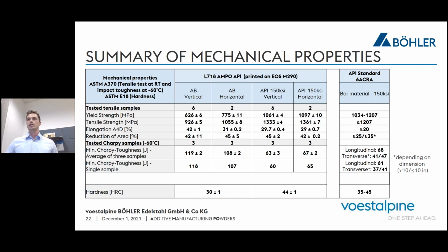On the right-hand side, you have the standard, so the API standard 6 ACRA, which is basically for the bar material, 150 KSI. And in the middle, you have the as-built vertical and horizontal values, as well as the API 150 KSI vertical and horizontal values. We need to say that this powder and these testing samples were printed on an EOS M290. And as you can see, when this heat treatment is applied, we are well into the standard range.